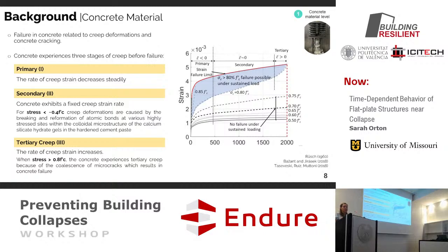Concrete experiences creep. So under sustained load, you can define essentially 3 stages of creep. One in which the rate of strain decreases, and so it's a primary creep. Another one in which it's almost constant, and then a third one in which it can have a sudden increase until failure. Most concrete materials, some sources say 80%, some sources say 70%, but if you load it up at a high level and leave it there, the concrete will fail over time.